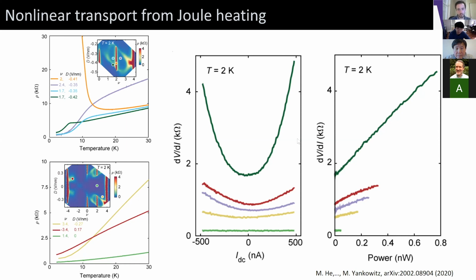Okay. So when you do these AC measurements, you always have to worry about a background signal, right? Where your zero is on your lock-in? That's right. And how do you calibrate that? I think we're probably not dominated by that because the zero DC current resistivity is very large here. We're talking about kilo ohms, and we're not trying to measure a few ohms. Okay. So if I look at this dV/dI versus I_DC, the green curve, does it change if you apply, say, 100 Gauss or 1,000 Gauss or a Tesla? It changes slightly. It changes quantitatively, but not qualitatively. Okay, so it's definitely not superconductivity then.